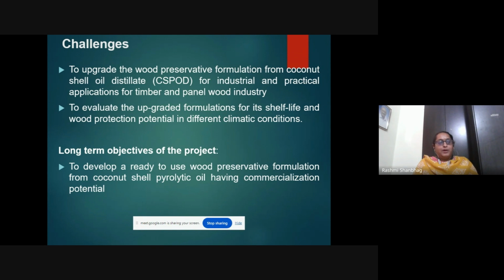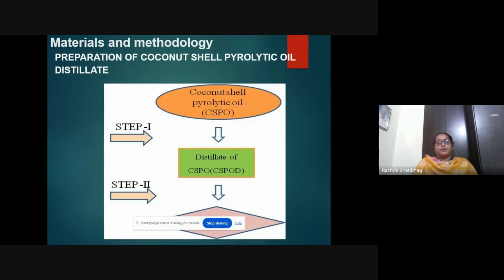Although we developed the preservative, the main challenge was the acceptance of this product in the industry. We tried with the coating industry, which means a kind of coating given to the wood. What we found is that there is a problem with emulsification; it is not mixing properly. Another major wood-related industry is the plywood or panel product industry. We wanted to use this product for these two industries so that there would be maximum utilization of this project. I'll explain how we prepared this.